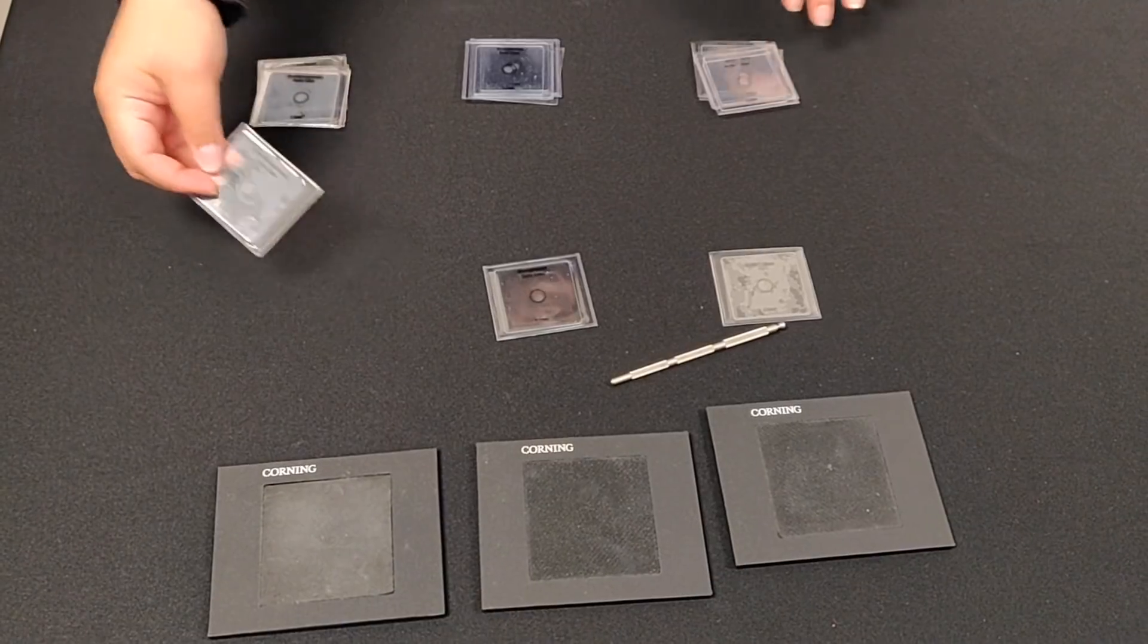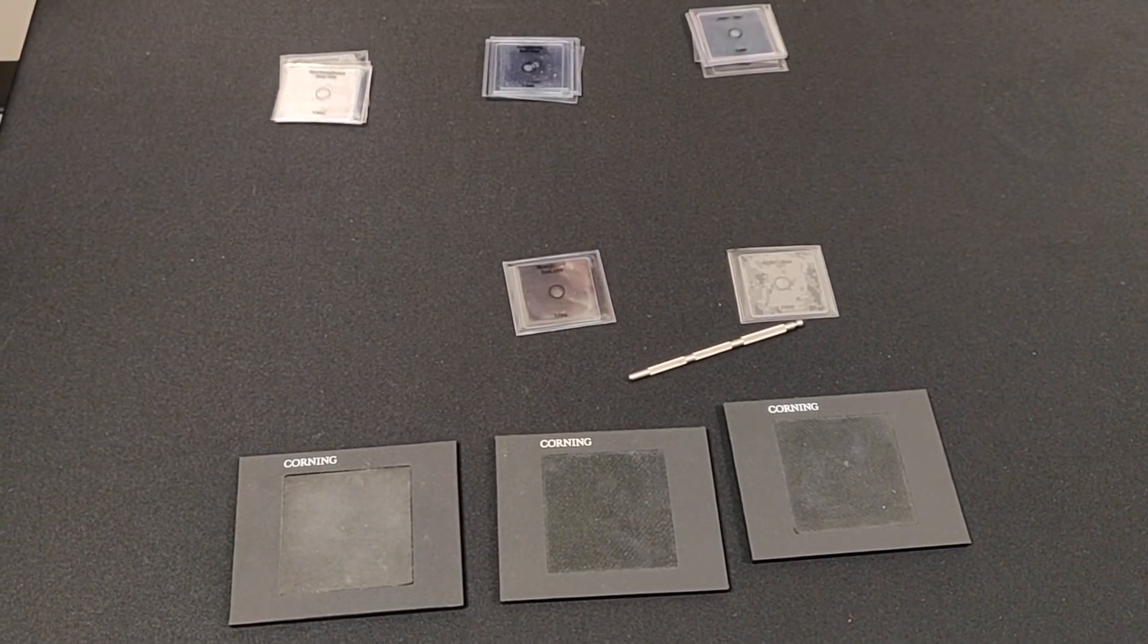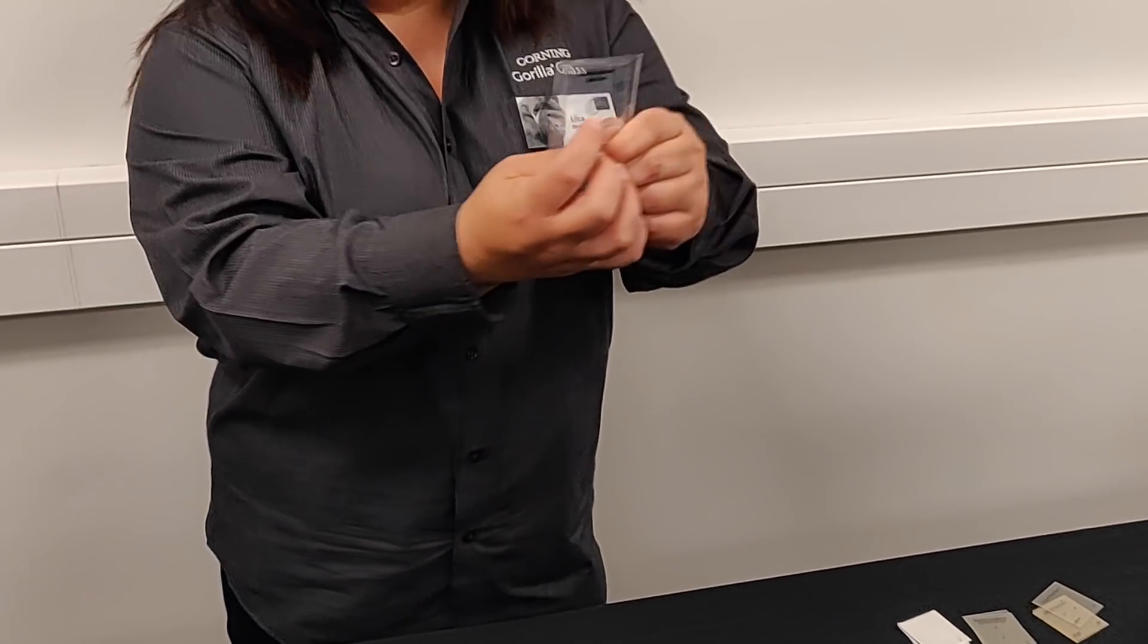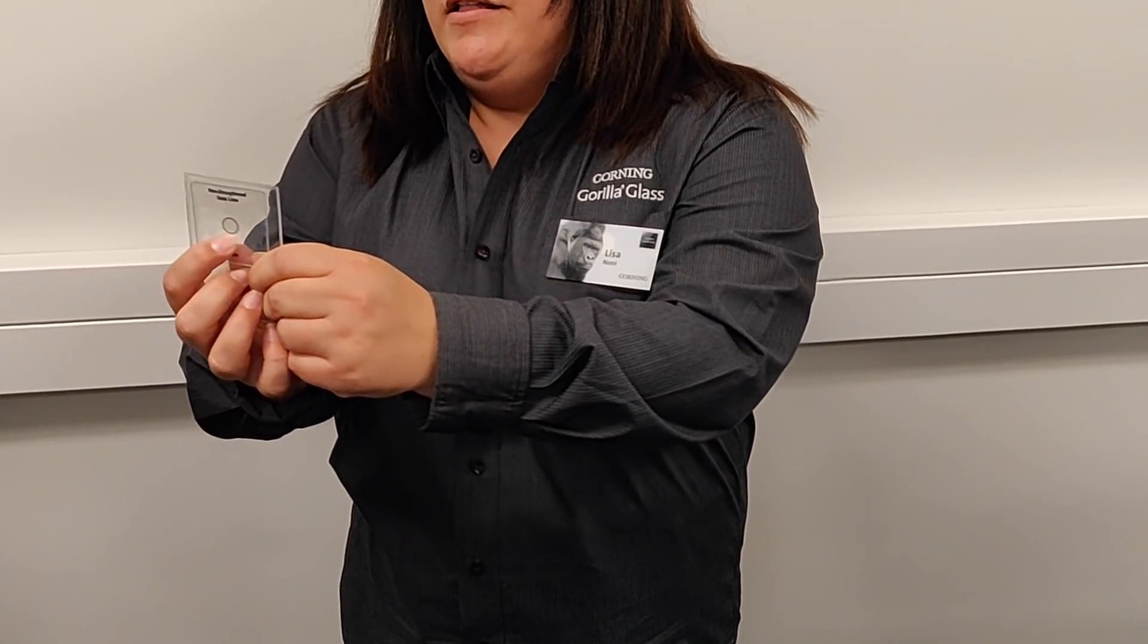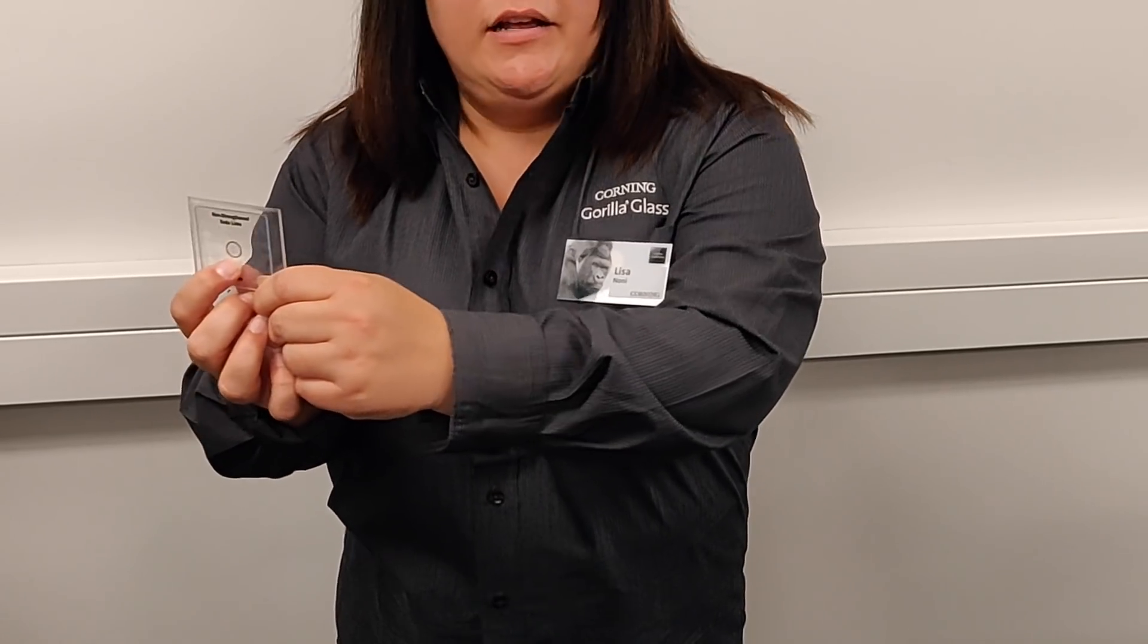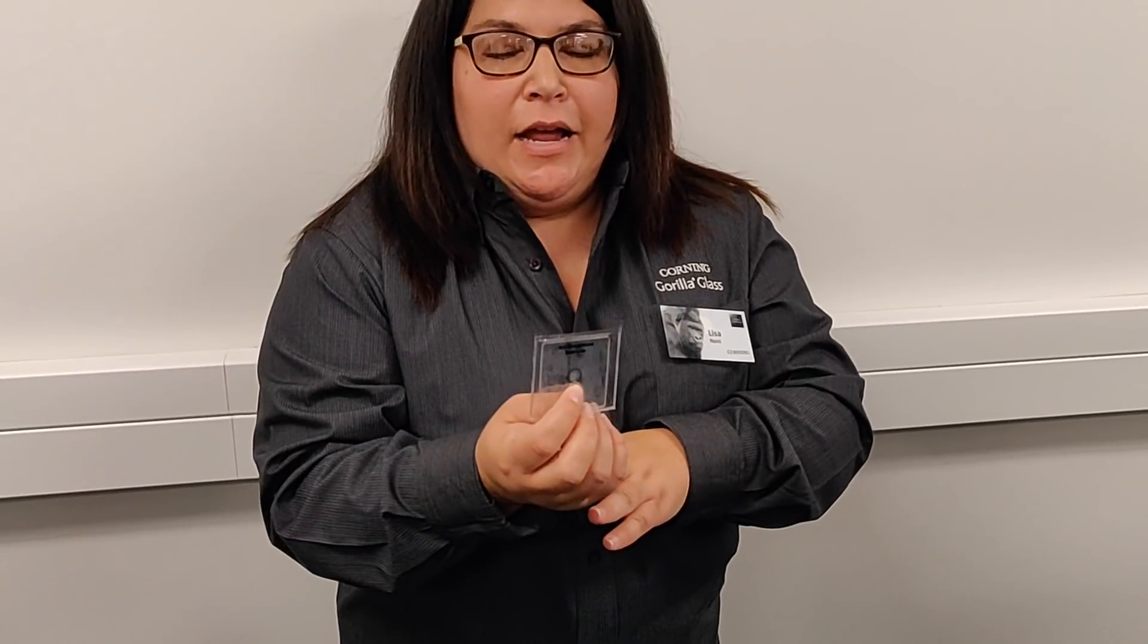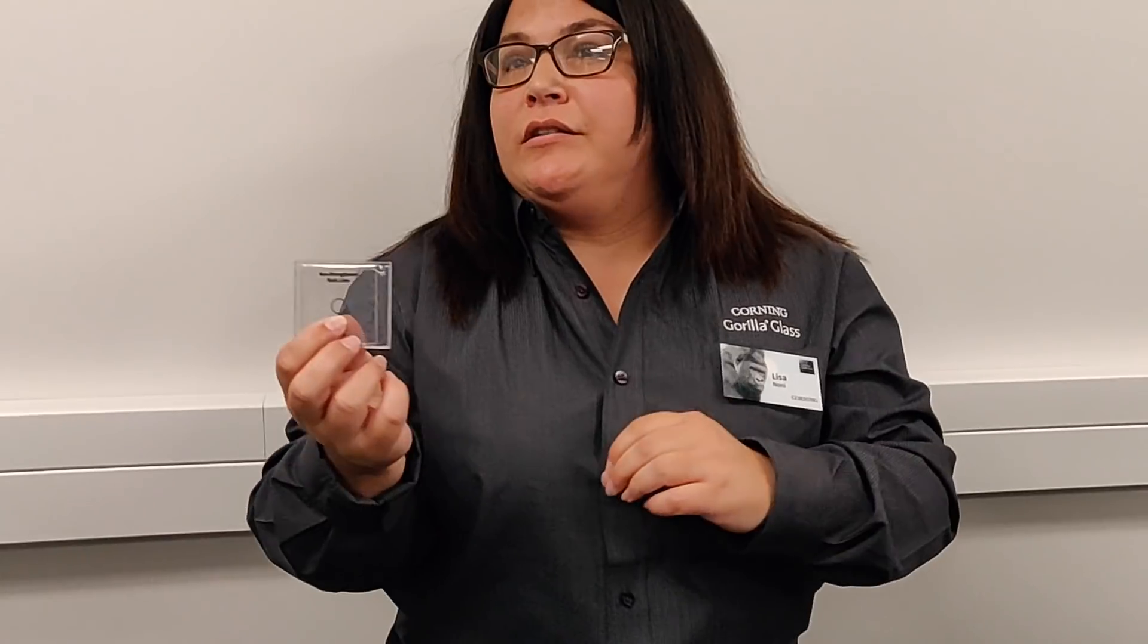All of these three glasses are the same thickness and if you look in the center there's a small shaded area that's actually been abraded. That's a silicon carbide particle abrasion and that is similar to sandblasting, and what we have found in analyzing devices that come back from the field is that this abrasion simulates the sharp contact damage that occurs in the field to handheld devices, and then it gives us a way in the lab to be more consistent with the testing and the damage introduction that we do.